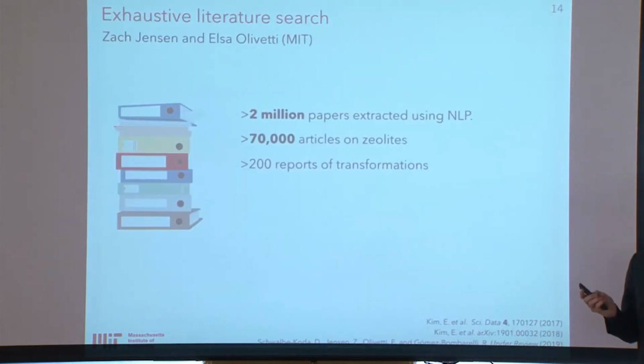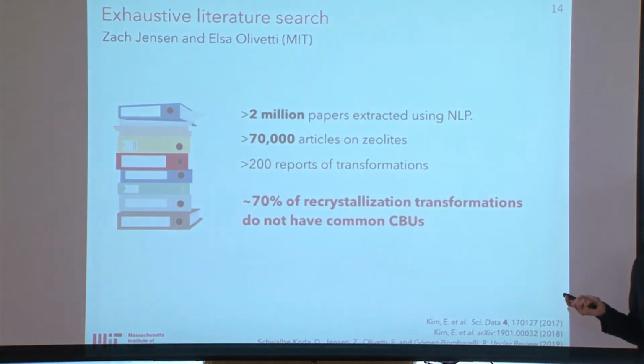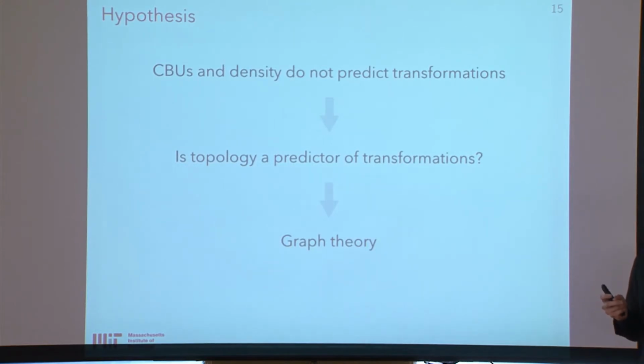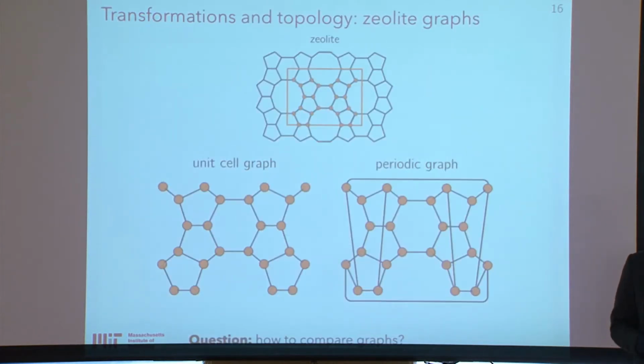To answer that question, we teamed up with Professor Olivetti here at MIT to gather the largest data set on zeolite articles from the literature. By extracting more than 2 million papers on material science using natural language processing and analyzing more than 70,000 articles on zeolites, more than 200 reports of interzeolite transformations were found. And to sum up the results related to the common building unit hypothesis, we found that 70% of the recrystallization processes do not agree with that hypothesis. When we analyze from the perspective of framework density, it doesn't work as well. So if these local structural features are not good predictors of such transformations, would the topology of the zeolites instead be a good predictor of how to convert zeolites? To go to that world, we resorted to graph theory and started representing zeolites as graphs.